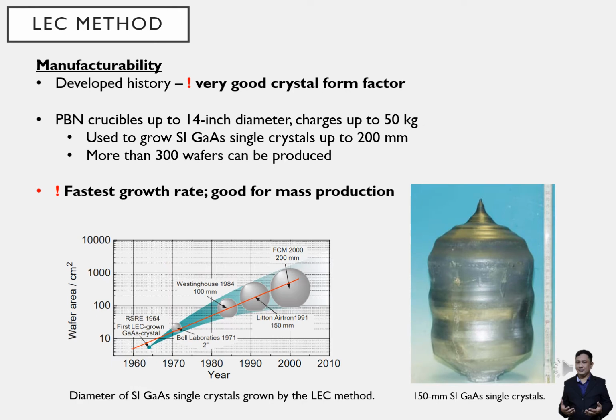In terms of manufacturability, LEC method has a developed history. It has a good crystal form factor. The PBN crucible is up to 14 inches diameter, can charge up to 50 kg, and thus is used to grow semi-insulating GaAs single crystal up to 200 mm. Also, more than 300 wafers can be produced. Fastest growth rate and good for mass production.